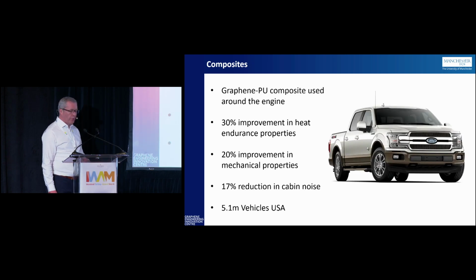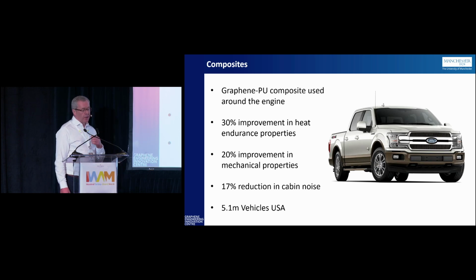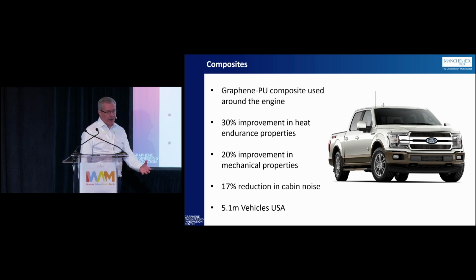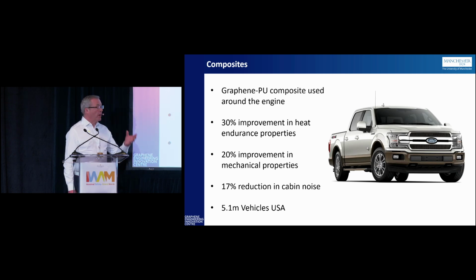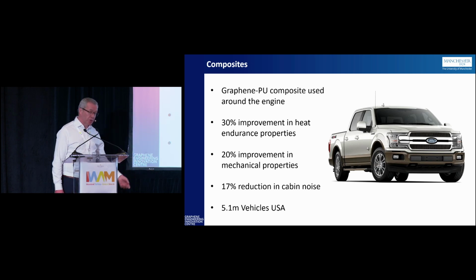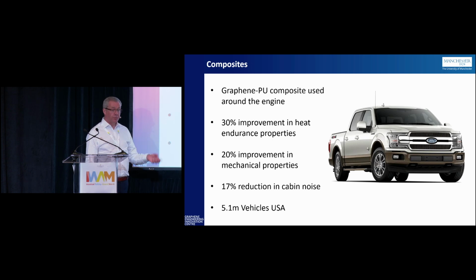Just one example of just how the automotive industry is adopting these materials. There was a particular polyurethane foam, and the project was around heat endurance for components. So this was looking at the supply chain, how do we get these performance materials into the supply chain that will give them the heat endurance, because it's about reduced maintenance on the components, reducing the stress on the components. So there was a 20% improvement in the mechanical strength, but also a 30% improvement on the endurance for heat benefits for this particular foam.